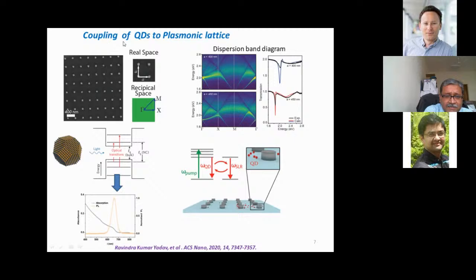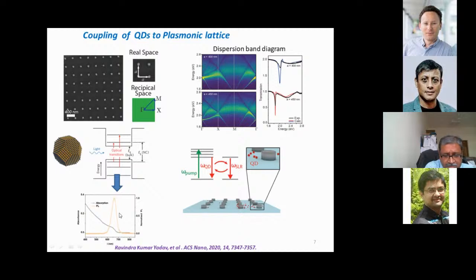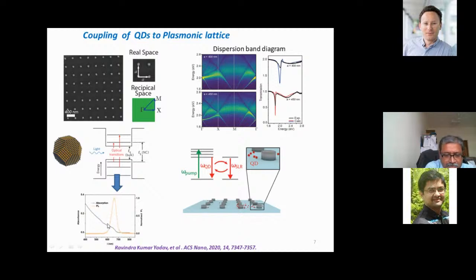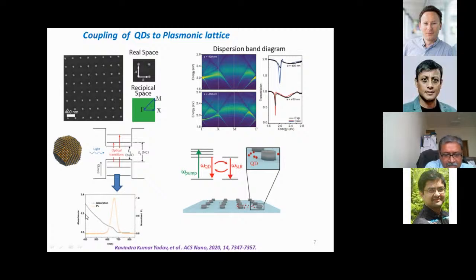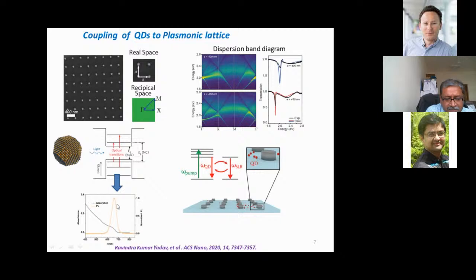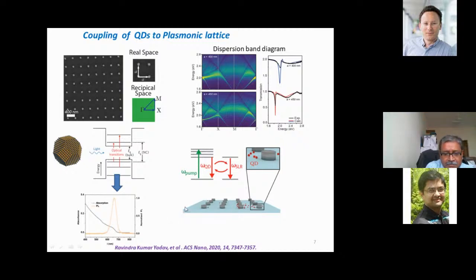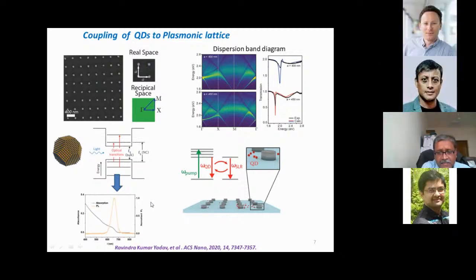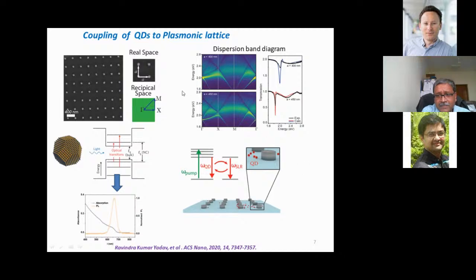So the idea is that we couple quantum dots, and the quantum dots in this case are cadmium selenide zinc sulfide capped core-shell quantum dots. They have very high quantum efficiency, and they have been used for almost 30 years or so, so they are very well studied and well known. The biggest advantage of these emitters is that you can actually tune them. Here you see a particular wavelength, but for a given material you can tune it over 100 nanometers or of that order. You can tune it through size and other methods, and then play around with how it relates to the resonance that you have, the lattice resonance.